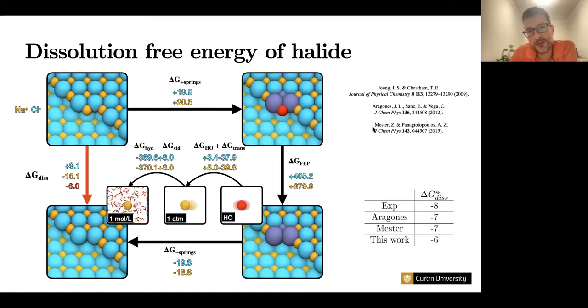So two completely different methods to calculate the same quantity. Hopefully this provides us a good reference. Our procedure, which can then also be applied for adsorbates, is to start from a slab, in this case of sodium chloride, that has a kink. If we remove an ion pair from the step edge, our final state will be exactly the same as the beginning, because it will be a kink with the same termination where we started from.